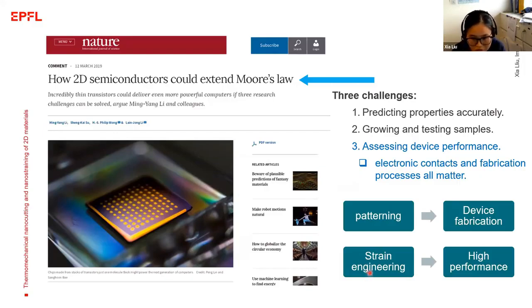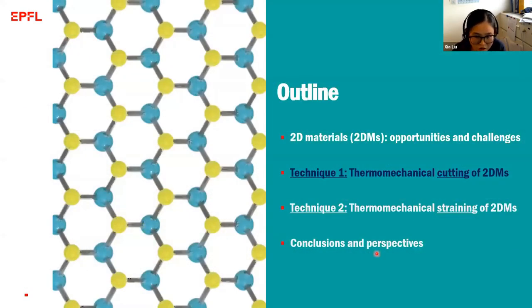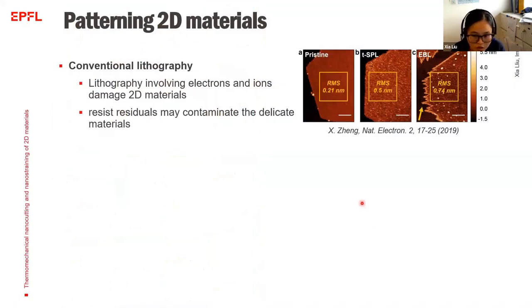So next, I will detail the two parts we have done here. The first technique I will introduce is thermo-mechanical nanocutting of 2D materials. When we talk about patterning of 2D materials, what comes to my mind first is conventional top-down lithography, including UV-based photolithography and electron beam lithography, which have been extensively employed. However, these lithographic techniques involve electrons or ions, which will damage the 2D materials, and the resist residues may contaminate the delicate materials. The image from Dr. Zheng's paper shows rounded particles present in the 2D materials fabricated by e-beam lithography, and flake damage happens at the edge.